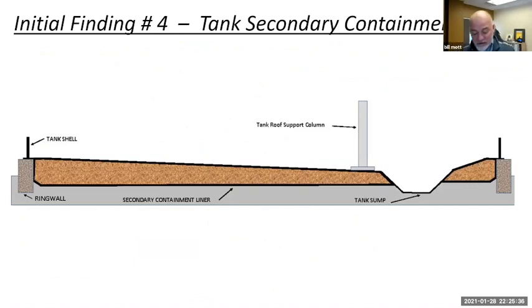I want to talk a little bit about their tank secondary containment systems. These are liners that run beneath the floor, under the sump, all the way up to the outer wall. They're battened down. It should be tight. Alyeska has been experiencing water accumulation between some of their tanks for more than 30 years. However, there are other tanks that are not accumulating any water. None of the annular plate extension ring wall seals have been maintained on any of the tanks. They're all subjected to 70 inches of rain a year.